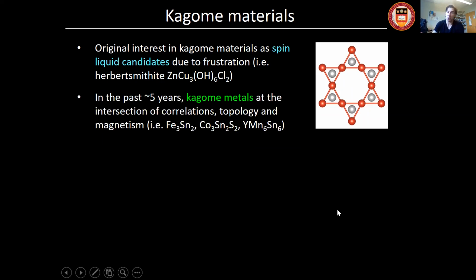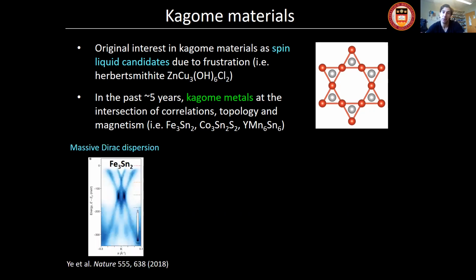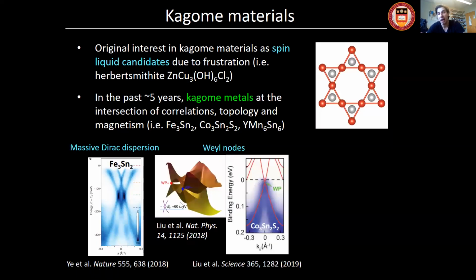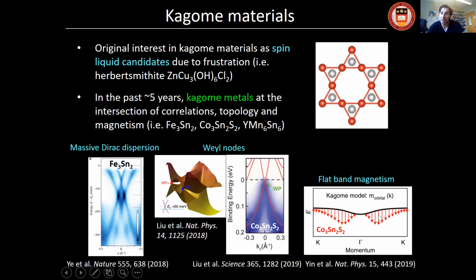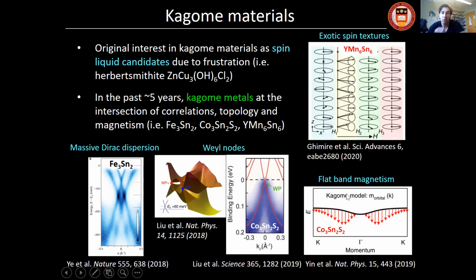In the past 5 or so years, magnetic Kagome metals were really at the forefront of this field. Systems like iron tin, cobalt tin sulfur, yttrium manganese tin, and so on. What unifies these is really the fact they're all magnetic in some form, either antiferromagnetic or ferromagnetic. Many of these interesting theoretical predictions were already discovered there. For example, Dirac dispersions, even Weyl points, in cobalt tin sulfur, and flat band magnetism. Flat bands were imaged, and interestingly, they generated this orbital magnetism that you can also visualize using STM. So there's been a lot of work there, but again, it all involved Kagome magnets.